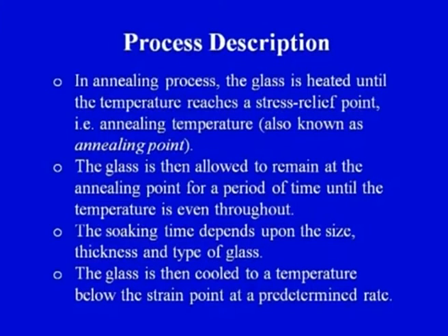So 2 important steps are heating. The glass is heated until the temperature reaches the stress relief point, and secondly we are maintaining the level at which we have raised the temperature. Third, the soaking time, or this holding time, we can also call this time the holding time. The soaking time depends upon the size, thickness and type of glass.